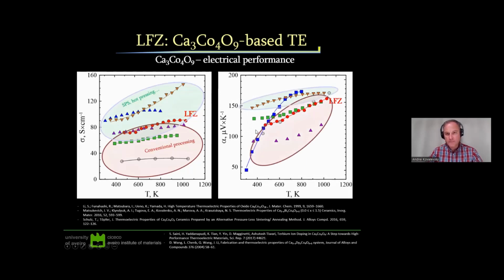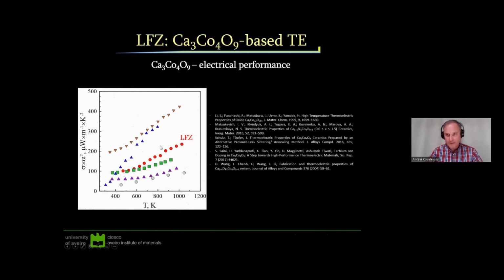The same applies for the Seebeck coefficient. And so we can eventually compare the power factor of this material grown by laser with the literature data.